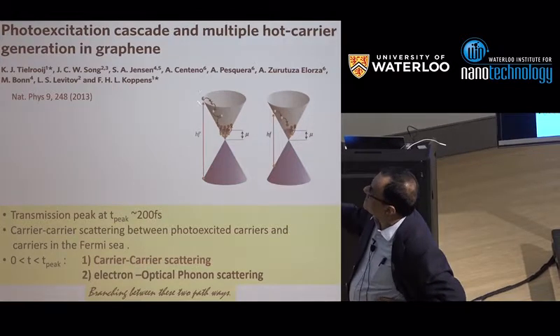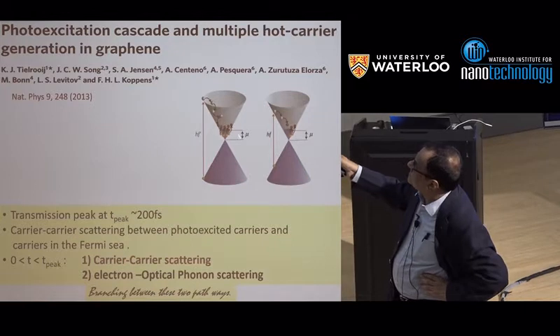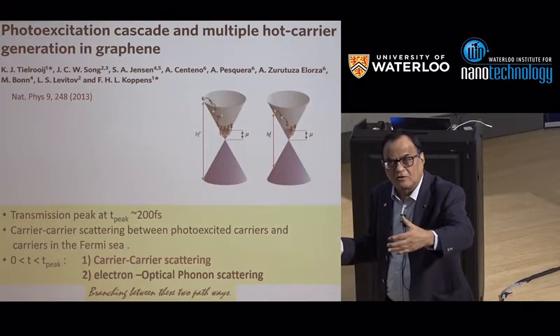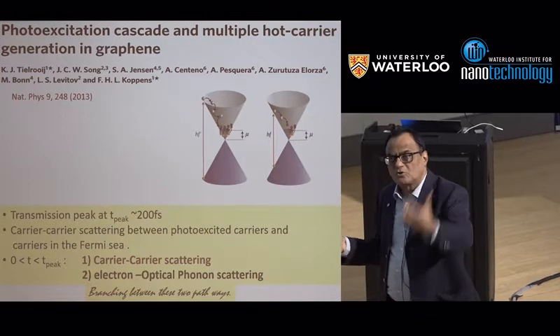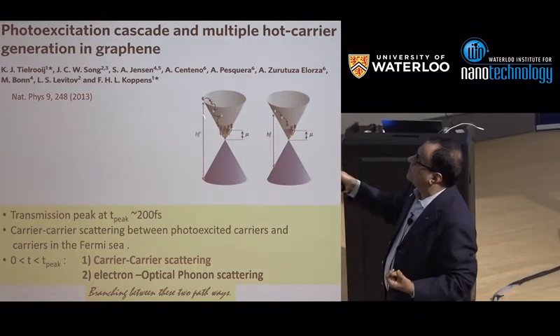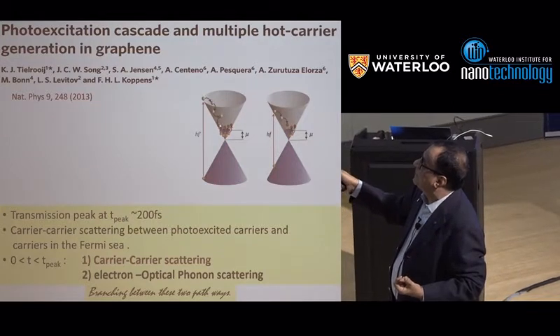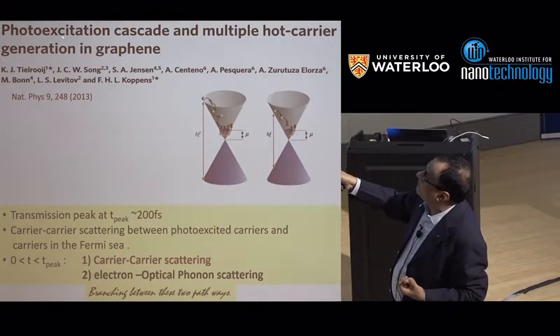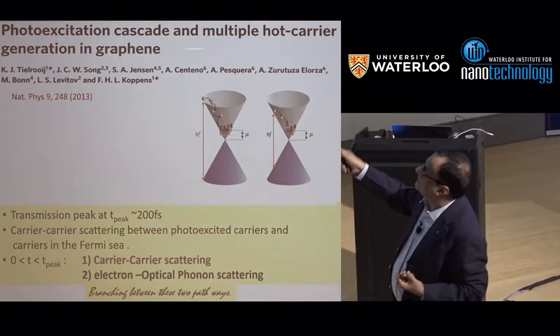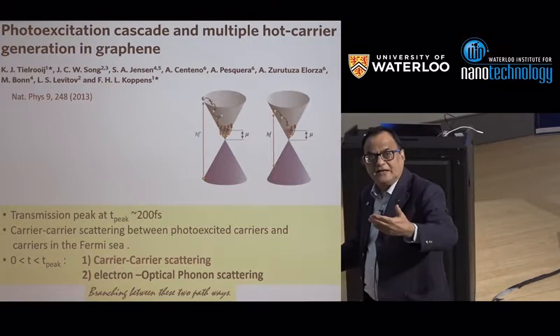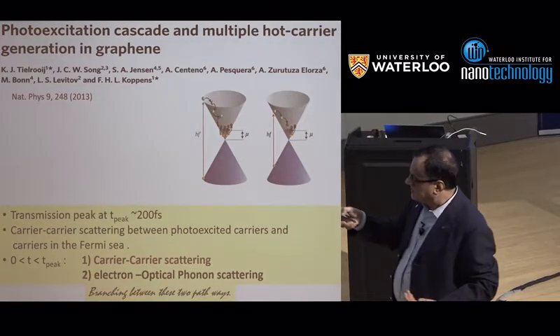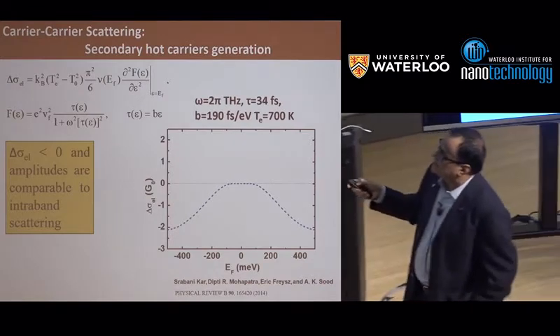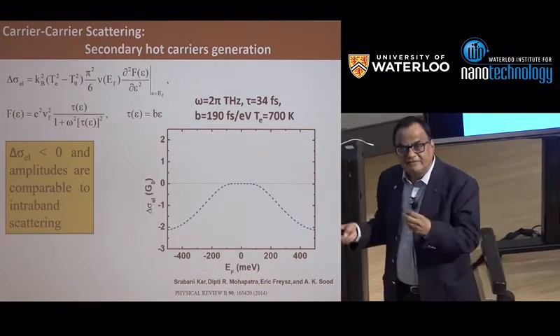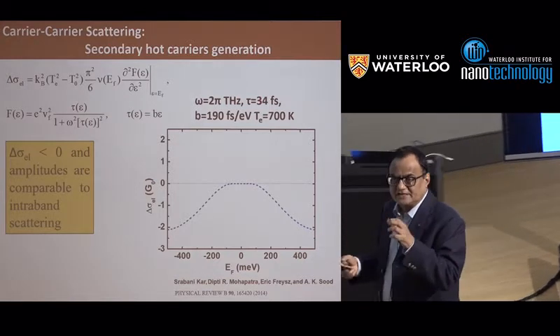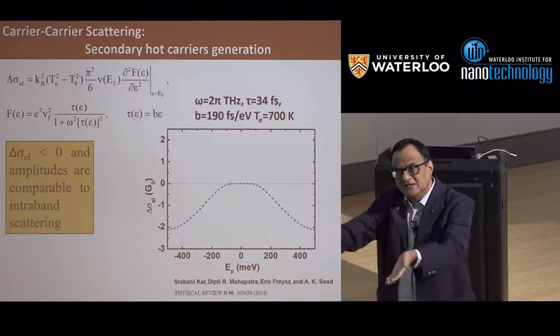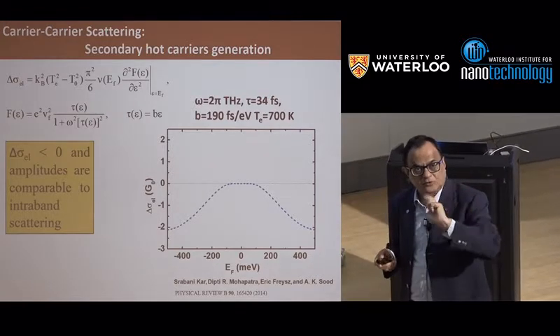So you get this photoexcited electron, and this electron interacts with the existing electrons which are already there in graphene. And because of the strong Coulomb interaction, it makes them hot. So this electron interacts with them and also makes them hot. So that is why it is called photoexcitation cascade and multiple hot carrier generation. So you get many hot carriers just with one photocarrier. And this can be quantified and shown that this mechanism indeed leads to conductivity which decreases on photoexcitation, because the lifetime of the carriers has changed because of this mechanism due to strong Coulomb interaction.